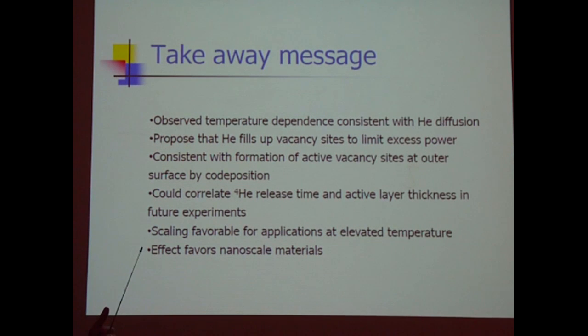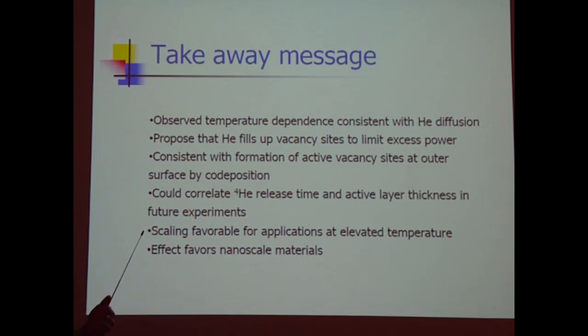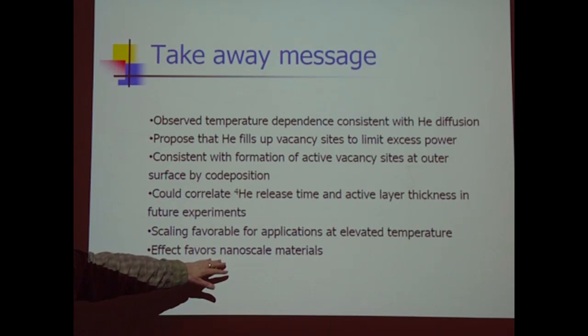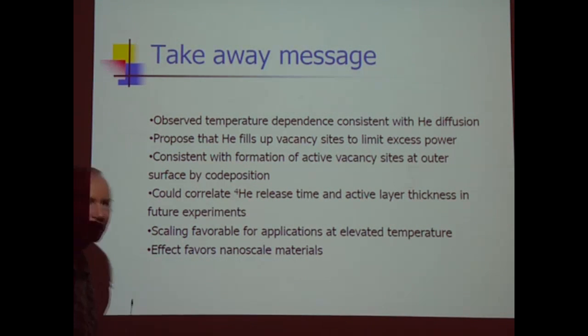As an experiment, that would be a doable experiment. It'd be interesting to see. And if you can measure the release time and correlate that with the distance and connect that with the diffusion of helium through, that would add evidence that this is actually going on. The scaling is favorable for applications at elevated temperature. The effect basically gives a gigantic leg up for smaller scale devices.